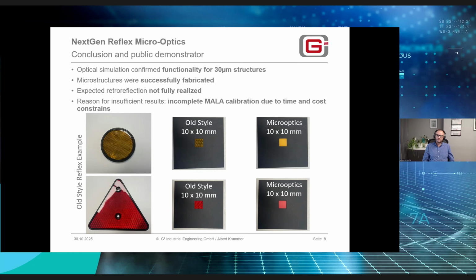The good thing, we clearly know the reason for the insufficient results, namely the maskless grayscale laser lithography calibration was not perfect. That means the machine used for this lithography was not perfectly calibrated, and due to the time and cost frame within this project, we had no chance to do a second loop. But yeah, it's well known where the problem was and how to compensate it.